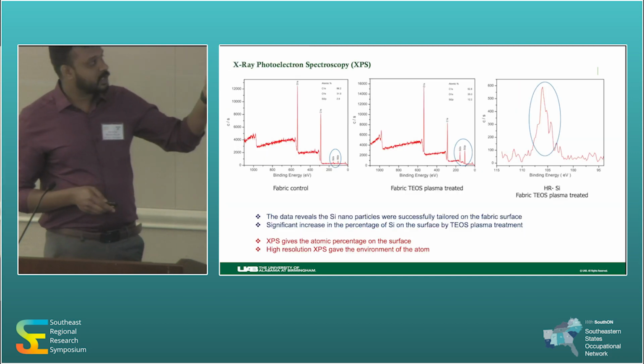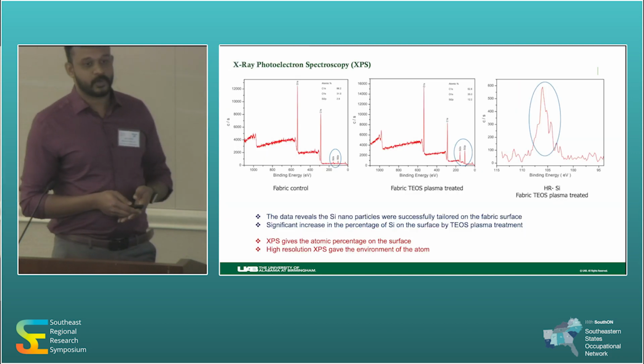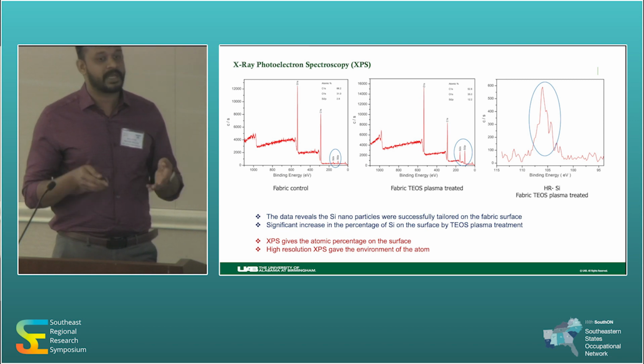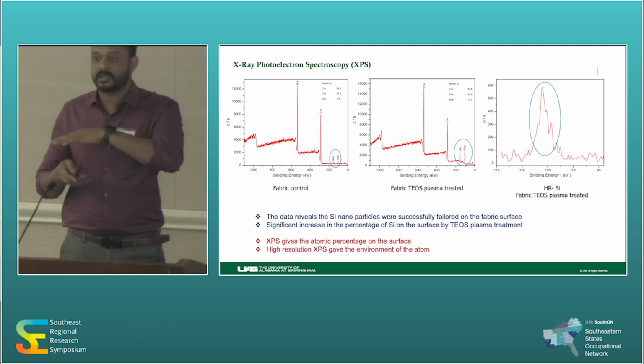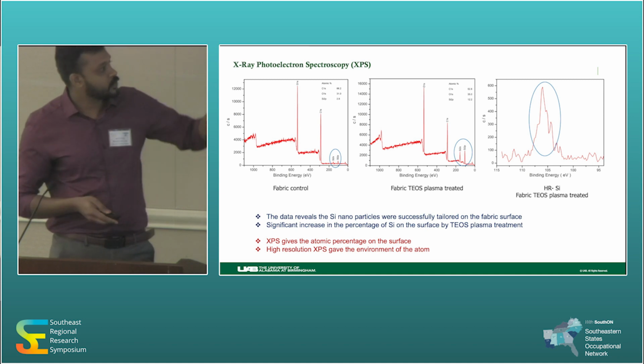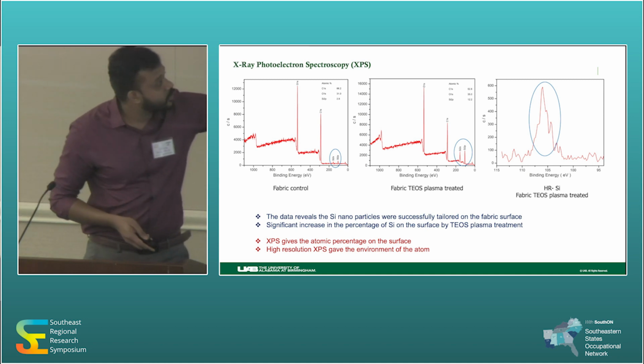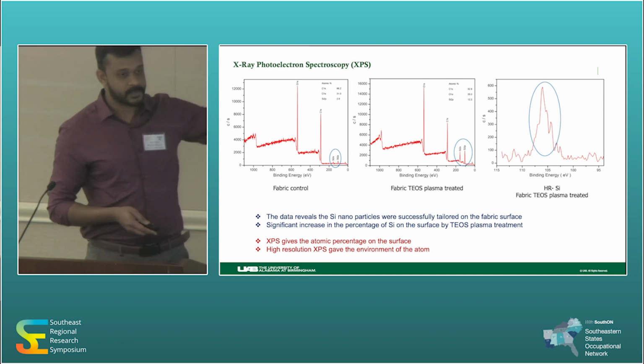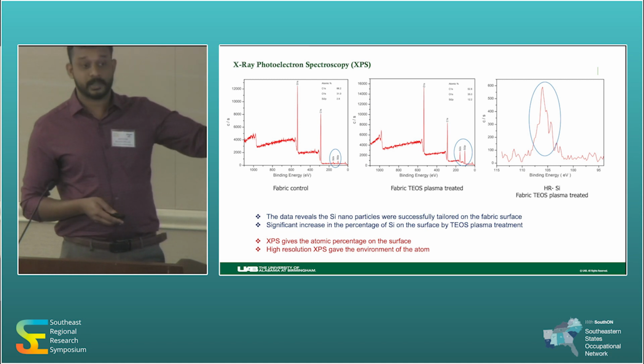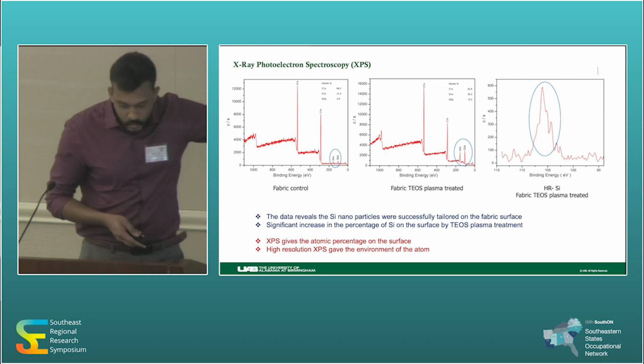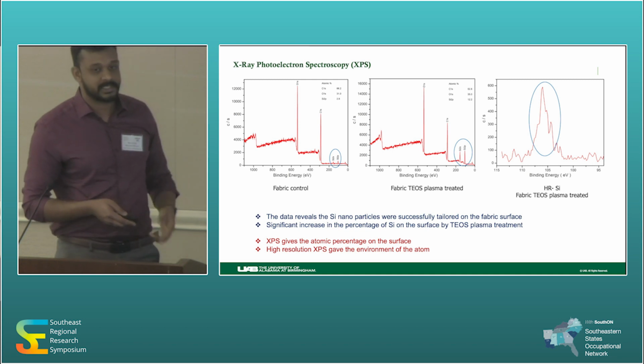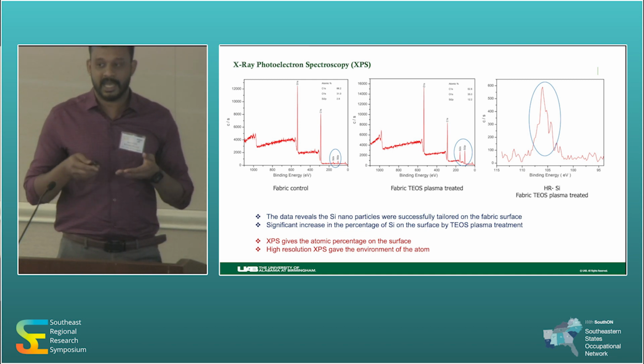So after plasma treatment, we tried XPS, X-ray photoelectron spectroscopy. This is basically for elemental percentage analysis on the surface of a substrate. With that, the control has almost 2.8% of silicon. Then after TEOS plasma treatment, it goes up to 12.2%. That means our plasma treatment is effective.